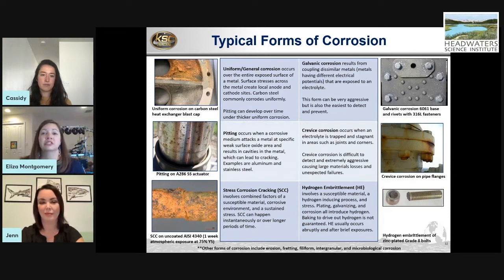And then crevice corrosion is configuration based, really. It's water wicking in somewhere and causing corrosion on the inside. Sometimes it's hidden, sometimes it's not. But those are things that we can control as engineers. As a design engineer or materials engineer, you can literally control this. There are a lot of things that are easy to control. And hydrogen embrittlement is similar to stress corrosion cracking, except that hydrogen is actually introduced into the base metal structure and causes embrittlement, but it fails similarly, where it breaks catastrophically.